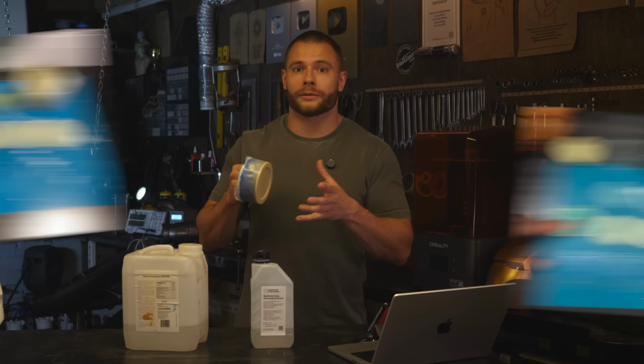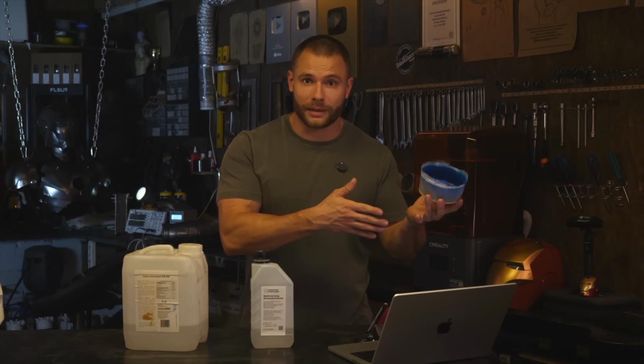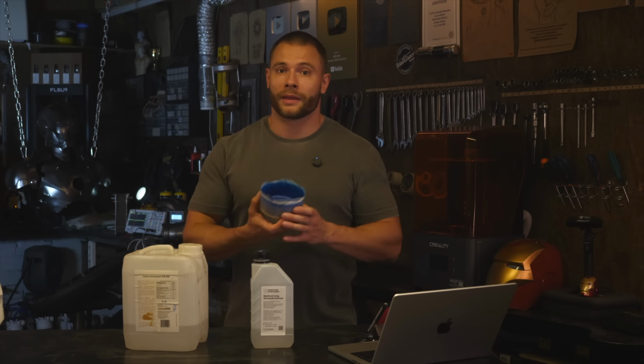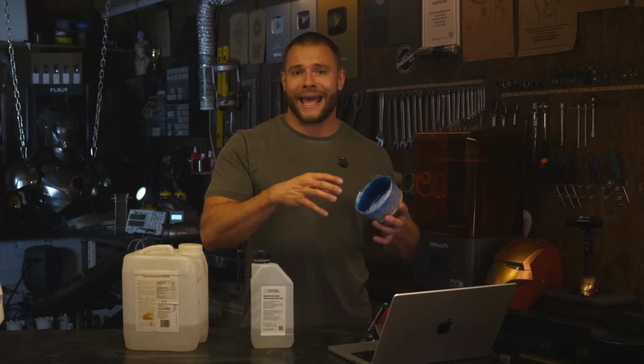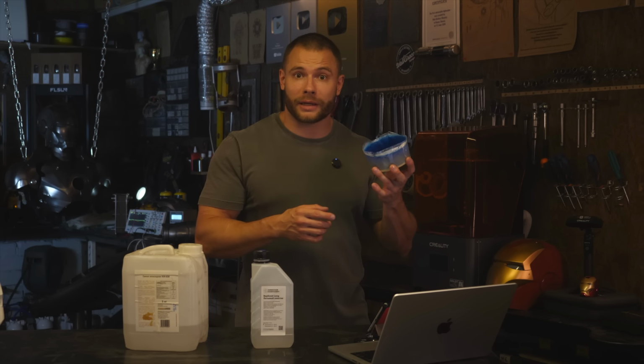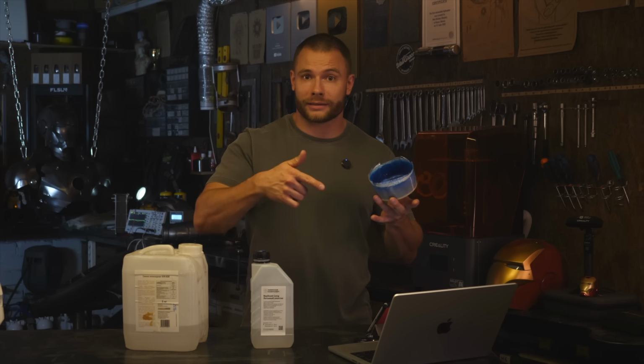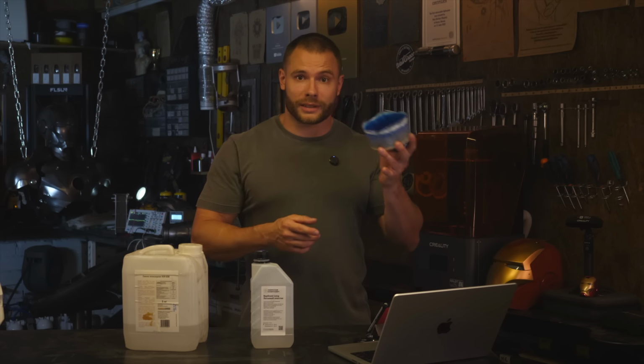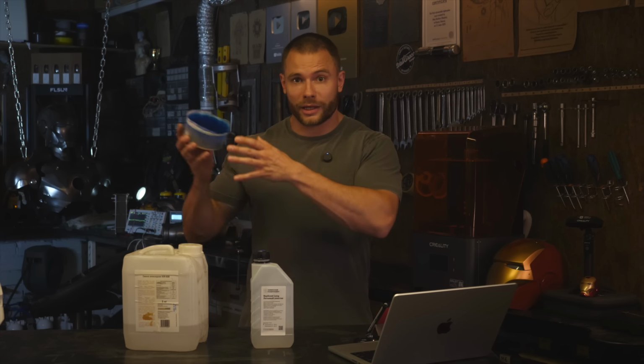You might say, Alex, couldn't you have, before all this long work, made small test samples of the plastic and tried to glue a piece of fiberglass cloth to them? And I'll tell you, I did exactly that, and everything glued perfectly. But any technologist will tell you that not everything that works on the test samples works on final parts. In this case, with small test samples, a critical factor was missing: the time interval required for applying the resin and laminating. With test samples, it's a few seconds. With large castings, it's nearly 1 hour and more.